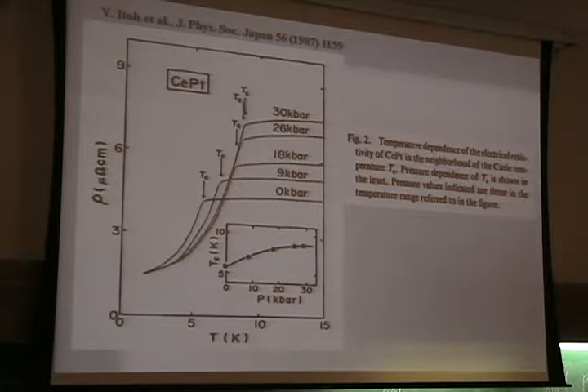measurement to check the kind of magnetic structure in this system. Okay, we're still looking to do this kind of experiment. But this is a work of Victor, where he did the first experiments in this system. And as he put the pressure, you see that the transition temperature goes up.